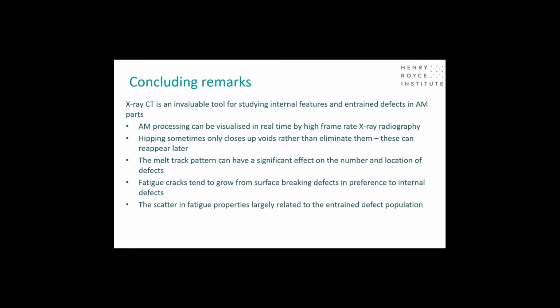The scatter in fatigue properties can be largely related to the defect population. There are, of course, other factors, and grain structure and microstructure can be important, but until we can really reduce the defect population to very low levels, defects tend to control the fatigue properties. And by obtaining the distribution of defects with CT, you can combine that with modeling to predict fatigue lifetimes.